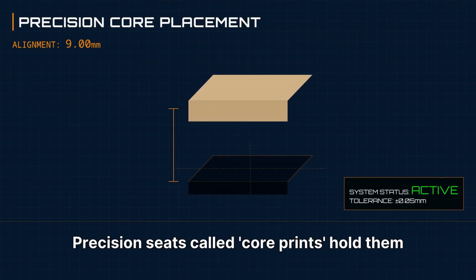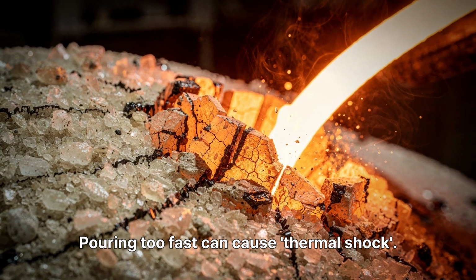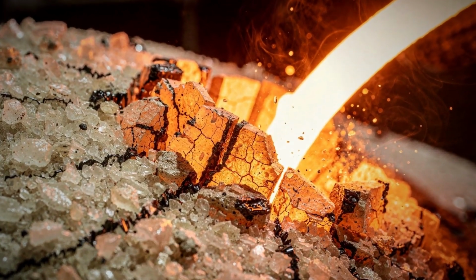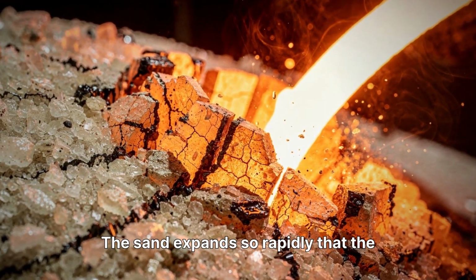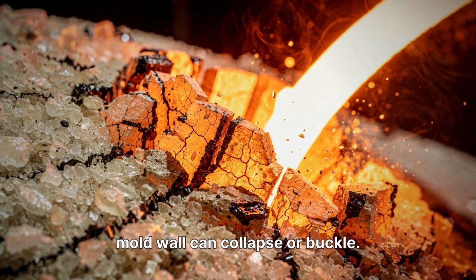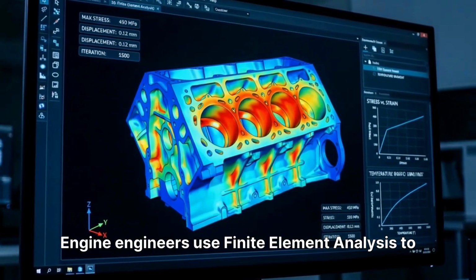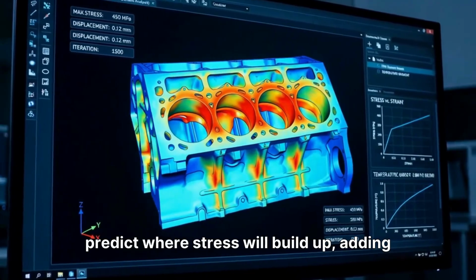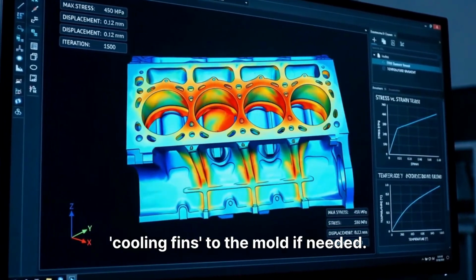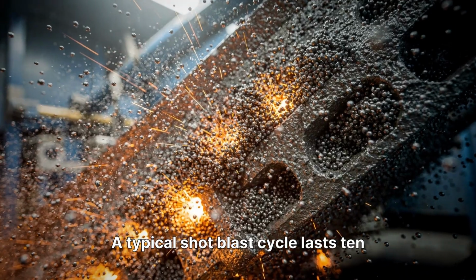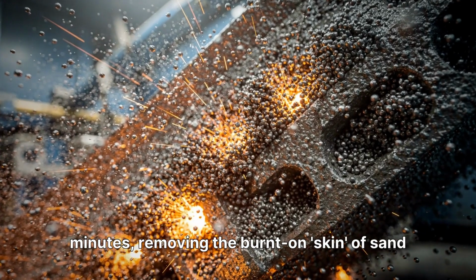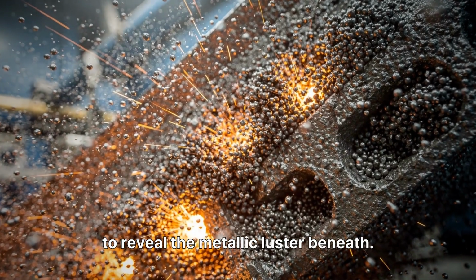Precision seats called core prints hold them in place. Pouring too fast can cause thermal shock. The sand expands so rapidly that the mold wall can collapse or buckle. Engine engineers use finite element analysis to predict where stress will build up, adding cooling fins to the mold if needed. A typical shot blast cycle lasts 10 minutes, removing the burnt-on skin of sand to reveal the metallic luster beneath.